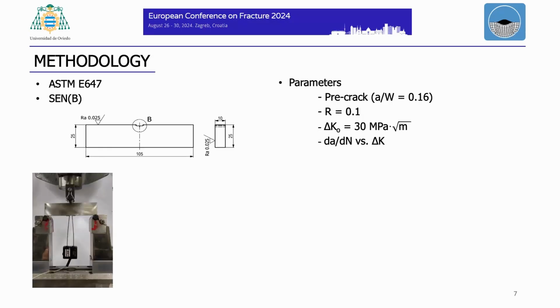We perform crack growth tests following the ASTM standard using SENB specimens of this geometry. For these tests, we use a pre-crack with this value, a load ratio of 0.1, and an initial stress intensity factor range of 30. And to obtain the crack growth rate versus delta K curves, we use an extensometer that during the test is measuring the COD. For the air test, we use the typical three-point bending device here.